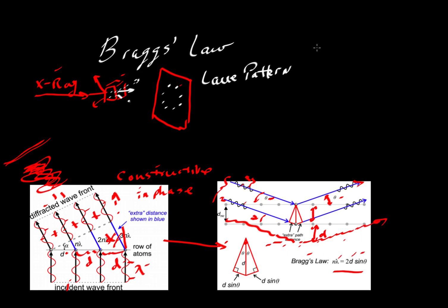Let's rearrange Bragg's law. We have 2 D sine theta divided by lambda equals n. We haven't explained this value of n yet, but this is where it becomes very important. We're going to take this value theta, the incident angle, take the sine of that angle, multiply it by D, this fixed D spacing for the crystal, multiply that again by 2 and divide by the wavelength. If we do that calculation and we get this ratio, then we look at the value of n. What the Braggs discovered is that if n is some whole number, that whole number could be anything, 1, 2, 3, etc.